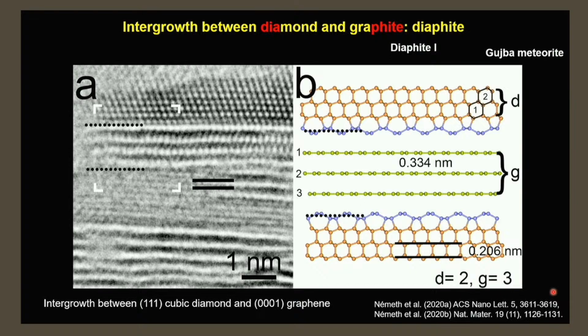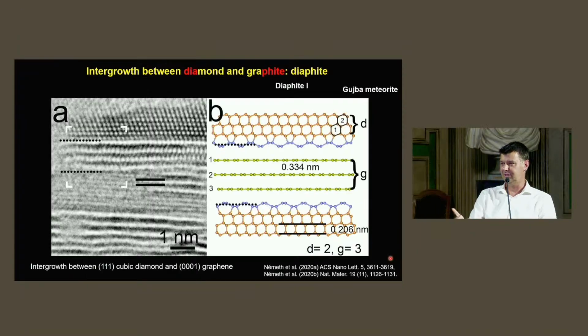And here in this slide I'm showing the first type, where we are seeing the 1-1-1 diamond layers and graphene layers on the top of these diamond layers. And if you want, you could say that there are two diamond layers, there is the interface, that's the blue region, and there are three graphene layers. And you can envisage lots of members of this diaphite 1 family. However, the issue which I would like to point out is that they are not ordered, so we didn't see three diamond layers, three graphene layers in a repetitive order. So anyway, this is the first type of diaphite.